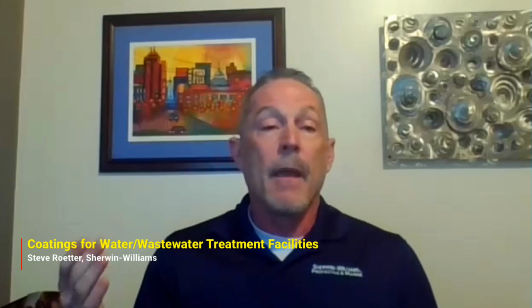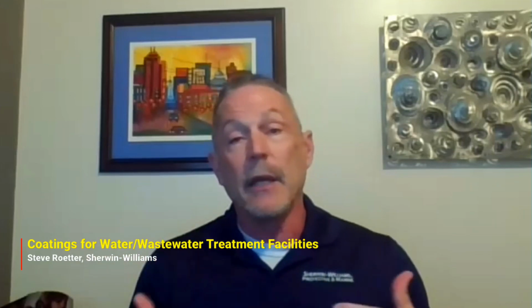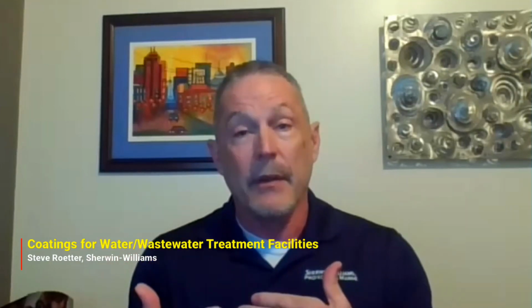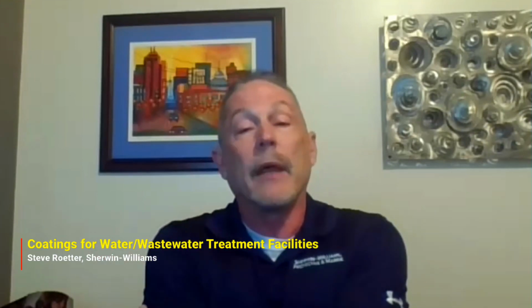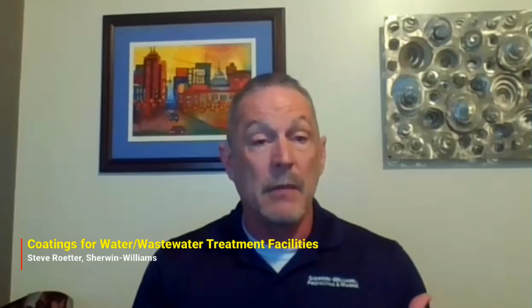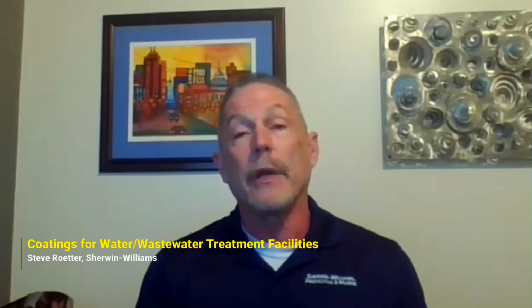The nice thing is that concrete surface preparation lends itself well to ultra-high pressure water jetting. UHP can remove a lot of concrete fairly quickly. Usually the removal of the concrete isn't the problem. It's the determination of how deep you need to go. That's the problem. So then, once the concrete's removed, a simple pH test of the surface of the concrete will give you a good indication of whether the surface is adequate. I like to see 9.5 as a minimum. 10 is better, but that's sort of where you need to be.